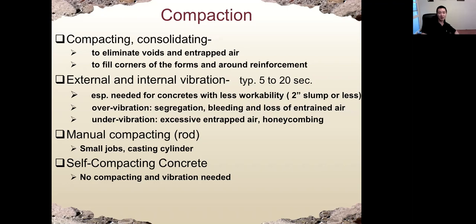We could use external or internal vibration, typically, depending on the job, around 5 to 20 seconds. When the workability of concrete is lower, for example 2-inch slump or less - we're going to talk about the slump test next week - we need more vibration or more compaction.